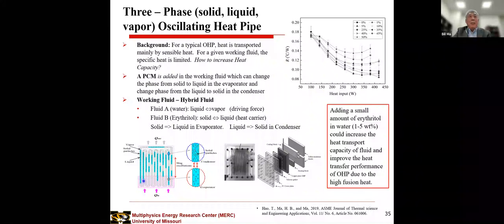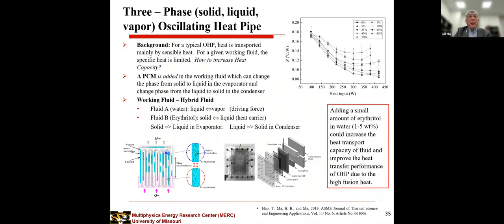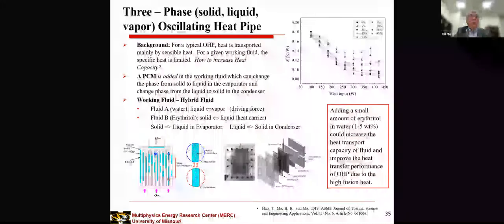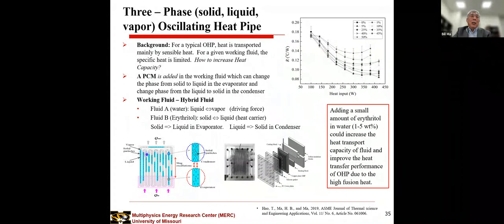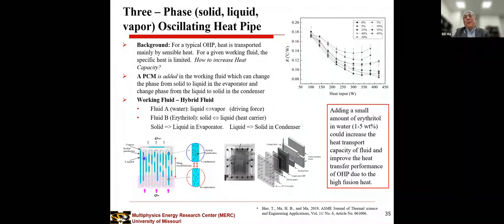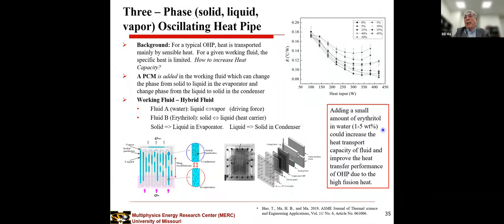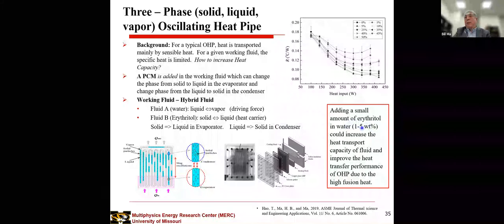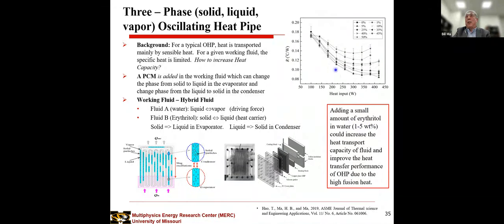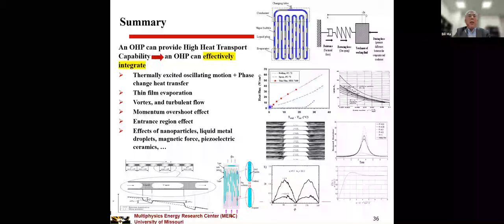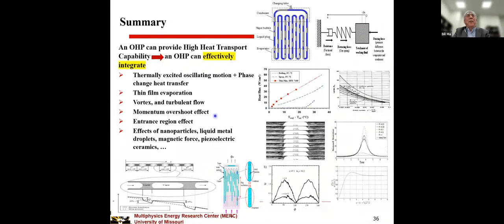When the PCM moves to the condenser section, it releases thermal energy, and the liquid PCM becomes solid. In this way, we can transfer more thermal energy from evaporator to condenser. The result found that with about 1 to 5% PCM, we can increase the heat transport capability of the oscillating heat pipe. So here is my summary.